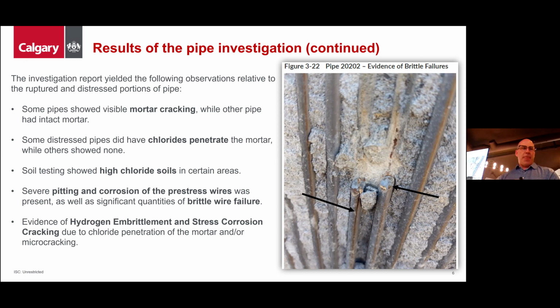My apologies. The investigation report yielded the following observations: that some pipes showed visible mortar cracks and delamination upon excavation, while other pipe had intact mortar. So, to your point, Nigel, some of the pipes did delaminate as soon as we had removed the overburden. The laboratory testing confirmed that some distressed pipes did have chloride attack that had penetrated the mortar, while other pipes showed that there was no evidence of chloride penetration. Soil testing along the feeder main showed significantly aggressive soils in certain areas. And we'll talk a little about that in an adjacent slide, because this is probably, for me, one of the most important points that we've come through right now. Predominantly due to high chloride concentrations.